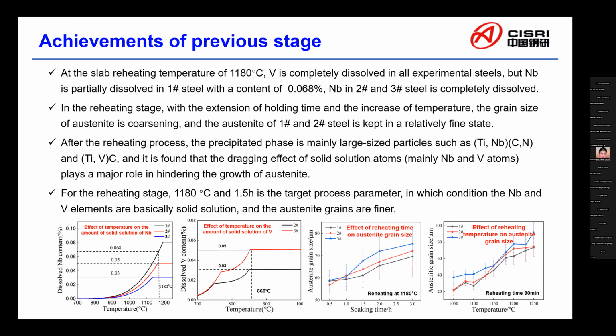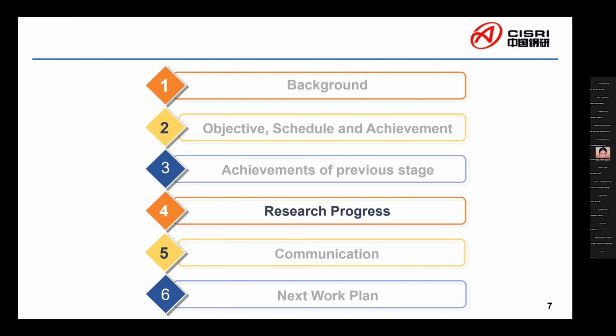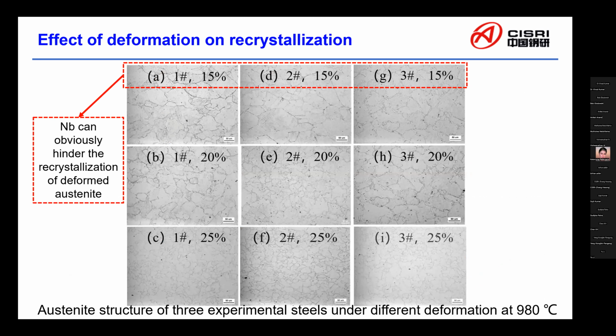For the reheating stage, 1180 centigrade and 90 minutes is the target process parameter, in which condition the niobium and vanadium elements are basically solid solution and the austenite grains are finer. And now I will introduce some results of our recent work.